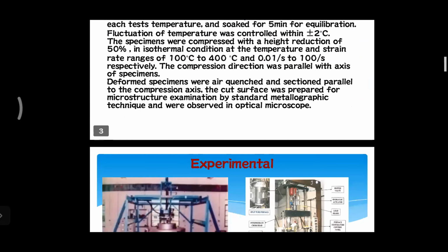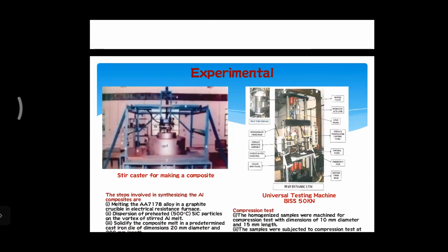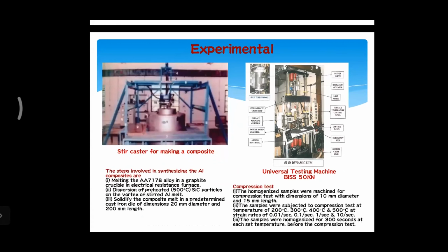The experimental setup is a stir caster for making the composite. In this, we first prepared the 7178 alloy, then remelted it and added 10% SiC particles to it. The particle size is 10 to 20 micron, and the BISS-make 50 kN universal testing machine is used for the compression test.